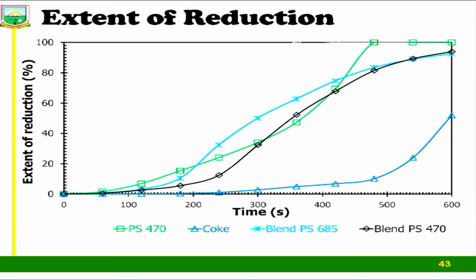And then these are the extents of reduction. If you take a critical look at this, you see that metallurgical coke is the last one, in the lower right-hand corner. If you want an idea about the efficiency of the process, anywhere any of the lines cuts the horizontal axis at the top, you drop a vertical line, and you can get the time for complete reduction. Within 10 minutes, metallurgical coke was doing only about 45% reduction.